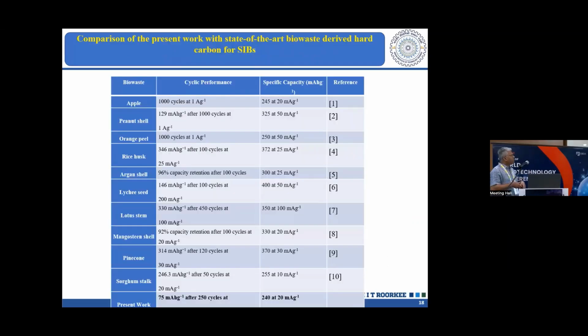Then when you compare this result with the previous researchers' work, some of the references were given. So if we talk about this, we find this is the capacity at 20 milliampere hour per gram current rate, which is relatively high, not very high, relatively high to sustain. So that gives around 240 milliampere hour per gram specific capacity. And this is the range that is given. This material was tested for the first time, and we are still in progress with this work, with some more studies. This is the present work.